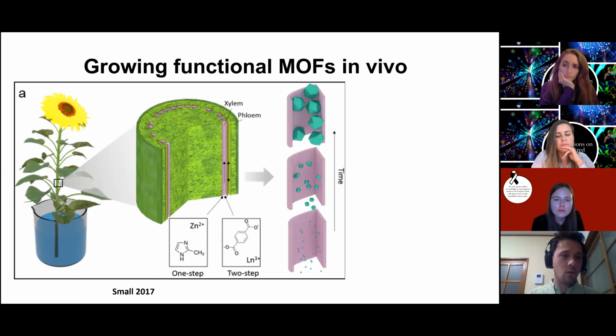We knew that protocol from childhood, that we could get materials up into the stem, and we incubated them with two different metal organic framework materials. One we did in one step, which was zinc and 2-methylimidazole. The other one we used rare earth metals, so that's Ln for lanthanide metals, and benzene dicarboxylate, because that has some inherent fluorescent properties when they're coupled.